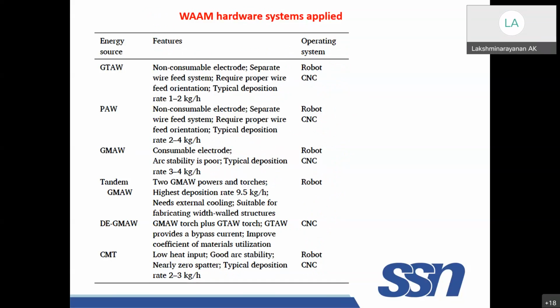Okay, and as I mentioned, you can use a robot or CNC just to deposit the material. As I mentioned, GTAW uses a non-consumable electrode, and you require a separate wire feed system. Orientation you have to control, because when you have the wire, whether with the horizontal it is 15 degrees or 30 degrees, that you have to optimize, so that your wire will feed into the arc column and your melting will be proper. In order to have proper melting, the wire should be fed at a particular orientation. This will affect your melting, and your deposition rate also.